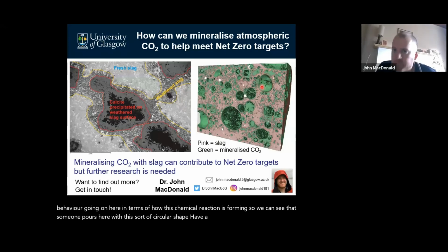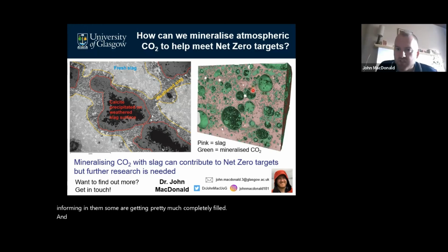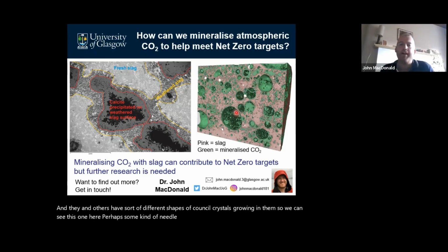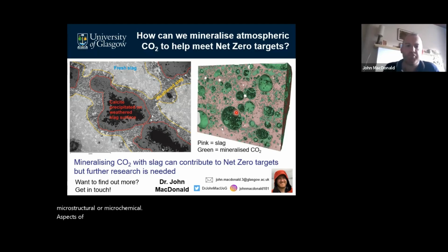And what's significant about this is that we can see that there is different behavior going on here in terms of how this chemical reaction is forming. So we can see that some pores here with this circular shape have a thin lining of the calcite forming in them. Some are getting pretty much completely filled, and then others have different shapes of calcite crystals growing in them. So we can see in this one here, perhaps some kind of needle shapes. So that's the microstructural or microchemical aspects of this chemical reaction that I'm particularly interested in.